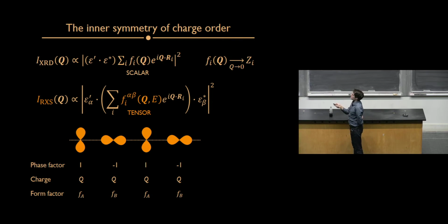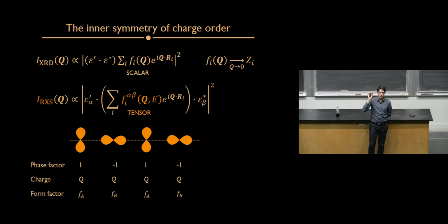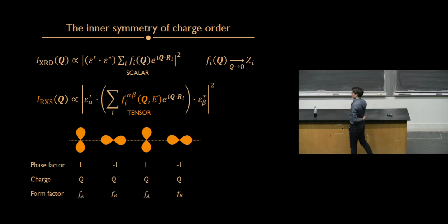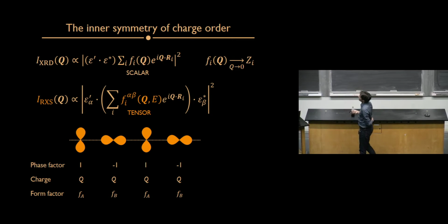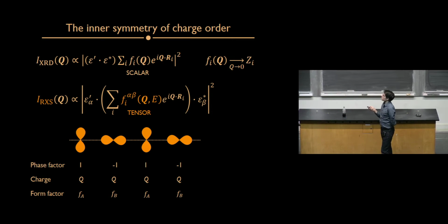This is basically a Fourier series, and the term in this Fourier series is the Fourier transform of the electronic density at a particular site. But for small q, which is what we're looking at here, this kind of converges to the total charge at that atom. So in the case of copper, that would be 29. In the case of oxygen, that would be, I guess, 8, and so on and so forth. In resonant scattering, the quantity we measure here is a tensor, and that tensor reflects the orientational local properties of the orbitals that are involved in that transition process. So this tensor for this vertically pointing orbital is different than the tensor for this horizontally pointing orbital.